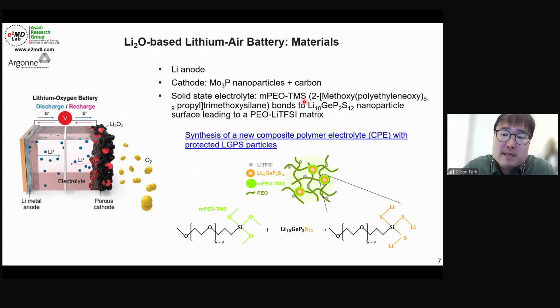Once they mixed these two materials, there was a reaction observed. The ether groups at the end of the mPEO-TMS chain react with the sulfur groups. So they made a silane bonding. Once they are mixed, the LGPS particle surface is well protected by the mPEO-TMS. And then by adding the long chain PEO and lithium TFSI as a conductor, we could get the CPE, a new CPE for the lithium oxide battery.